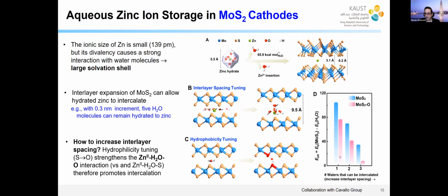Look at the blue and the pink. No matter the number of water molecules around the zinc, you will see when you have oxygen incorporated in the molysulfide, you will reduce the barrier to nucleation. And this drop along the y-axis, this is a calculation. If we increase the layer spacing, basically we are allowing more waters to be intercalated. And if you allow more water to be intercalated, because of this arrangement, then the barrier for intercalation becomes low. So that was the strategy.